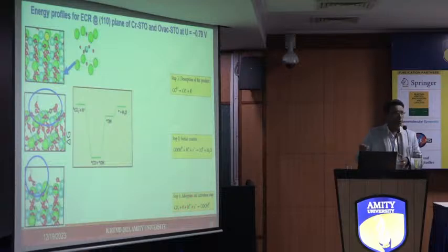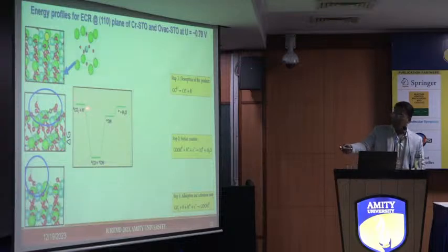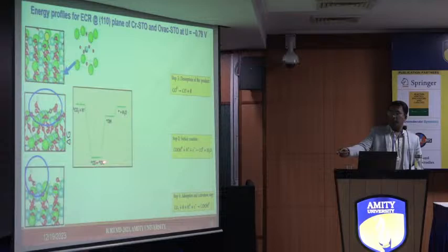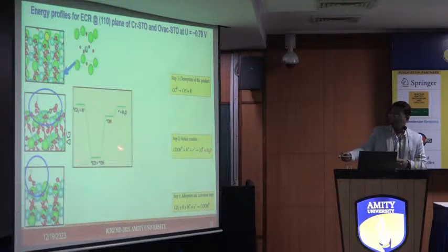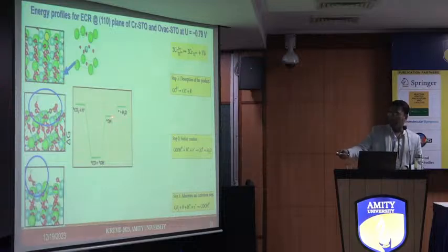It also abstracts the proton from the water, and it makes the COOH on the surface. This is a very facile process because you can see this is an exothermic process. Now, once this is done, the next step is the breaking of the COOH into the CO, which is adsorbed on the surface, and the water molecule. So CO is formed. This is also a feasible one, but next, when we go to the desorption step, this OH, which is being formed there, has to dissolve as a water molecule.